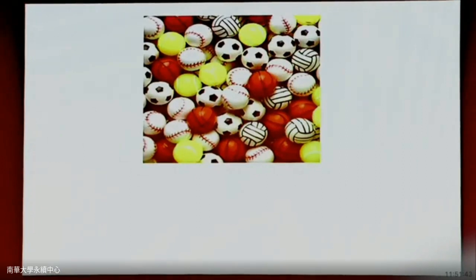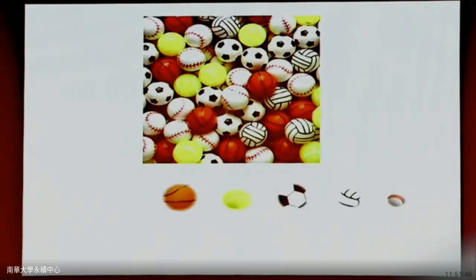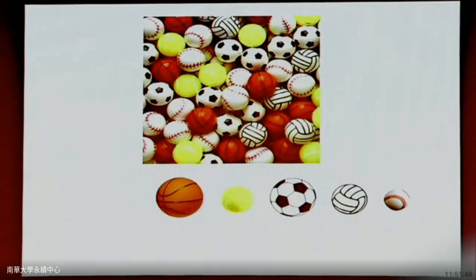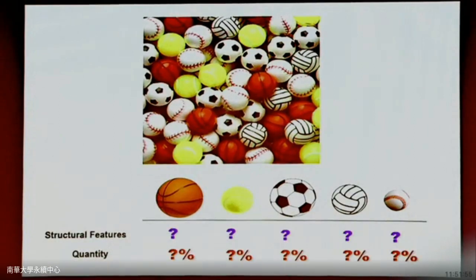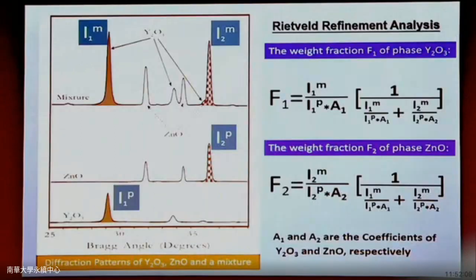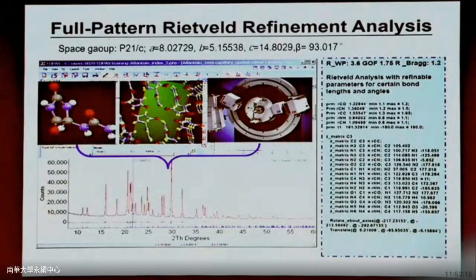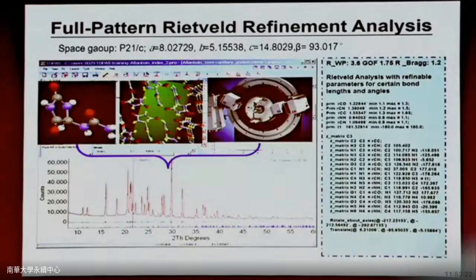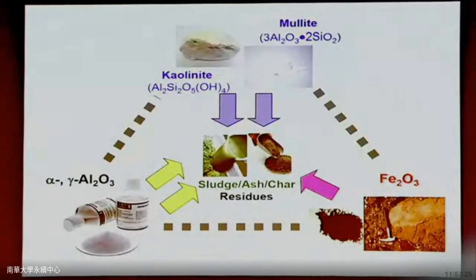And it needs to be quantitative because our natural system is actually a very mixed world. Right? We should not only know who they are, but we should also know how many of them. Because in the industry, you cannot just say, hey, I have 5 members right there, but 90% purity and 10% purity is a completely different value in the industry. Sometimes it is even the case for fertilizer, for example. So we try to use atomic structure simulation to analyze our X-ray diffraction patterns, and I use the X-ray diffraction to quantify each phase coming out. So that's been one of the strong powers that we have in terms of the techniques.